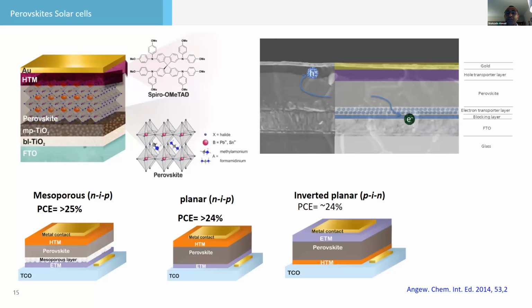The mesoporous, when you take titanium dioxide, we call NIP. This is the most efficient device configuration, which gives you 25% here. You can even get rid of the mesoporous. You can take titanium, tin oxide or zinc oxide. So you have a normal NIP structure. The efficiency is also 25% reported.